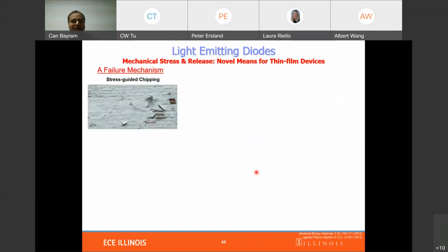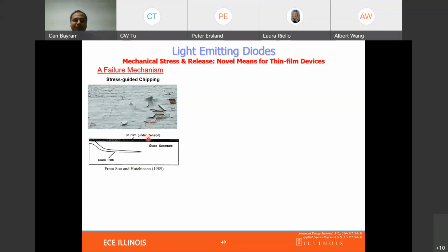Now, this mechanical release technique is something that we see every day. Typically, you notice it if you are a homeowner or just walking outside an old building. You might notice paint coming off the wall, and when the paint is coming off, it also chips part of the wall structure. This is indeed called spalling, the spalling failure mechanism. When you have a film under tension, you create a crack, and this crack also takes part of the substrate, or part of your wall in this case.